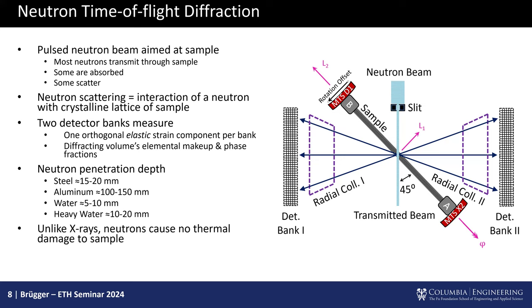Neutrons can go through about 15 centimeters of aluminum and about 15 millimeters of steel. This gives us a penetrating capability that does not alter the system mechanically. High energy x-rays from a light source will heat up material and burn biological samples relatively quickly. Neutrons, by coincidence, operate in the energy range of room temperature, so they cause no thermal change because they're the same temperature as the material. They also don't cause stresses and strains, so from a mechanics standpoint, the measurement is completely oblivious to the material.